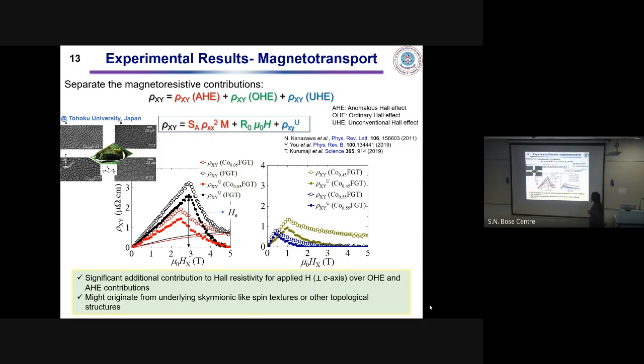So, what we have observed is this, but later on from Lorentz TEM, it was shown that they are magnetic skyrmions only. And we also tried to do magneto-optical Kerr imaging with a higher magnetic field, and we have sent the samples to IIT Kanpur, but we don't have the data right now. Which group? Satyajit Banerjee.